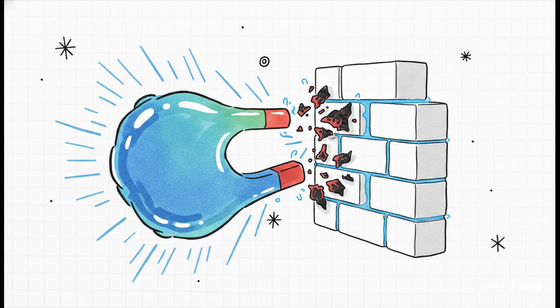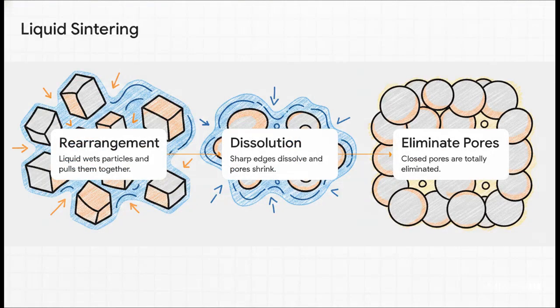It basically acts as a magical glue during the baking process. When you mix yttrium oxide into the raw powder and crank up the heat, it chemically reacts with that stubborn surface oxygen on the particles. It literally pulls the enemy oxygen right out of the aluminum nitride lattice and traps it into these secondary aluminate phases. So it cleans the crystal while simultaneously creating a liquid that helps glue the whole thing together. It's brilliant. We call this intense, high-temperature process liquid phase sintering, and it happens in 3 distinct steps.